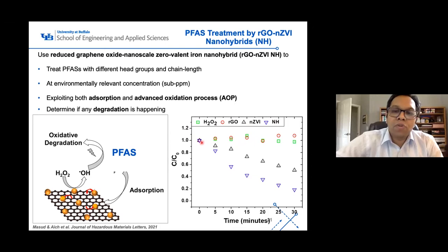So we expose these materials to this hydrogen peroxide and see how much of the hydrogen peroxide decays. What it means is, how fast this hydrogen peroxide decays means how fast hydroxyl radicals or reactive oxygen species are being generated by the catalytic property of these materials. So this is kind of an indirect way to compare these materials. What we have seen is the fastest decay of hydrogen peroxide was by the nanohybrid. So we wanted to see if that also increases the degradability of the PFASs or can adsorb the PFASs more.